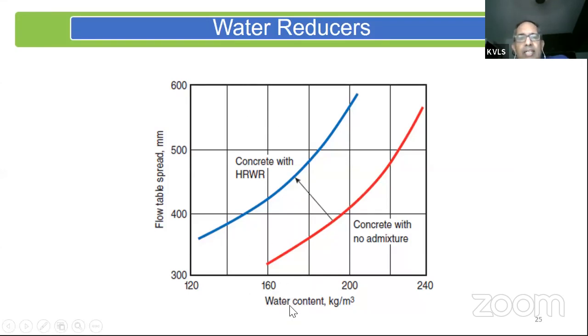That is shown here. The water content is shown on the x-axis, and the flow is shown on the y-axis. So if I make concrete, and if I increase the water content, I achieve a certain flow that is shown by the red line. But I can reduce the water demand. That is, I can achieve the same flow with a lot lesser amount of water in the concrete, as shown in this blue line here. So my concrete with the high range water reducer, HRWR stands for high range water reducer, basically gives me the same flow with a lesser amount of water, hence the term water reducer.